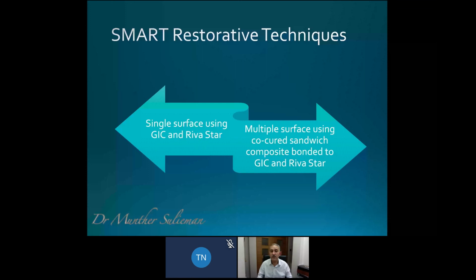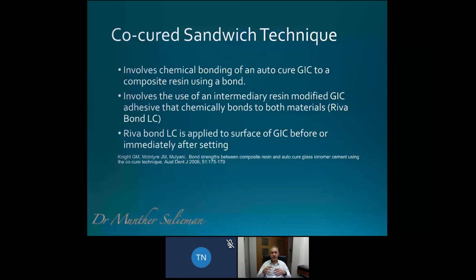The product itself uses glass ionomers just like the original sandwich technique, except in this case, what we're actually doing is we are using a chemical cured glass ionomer, so Riva self-cure or Riva self-cure heavy body. After you've used the Riva Star on a class 2 cavity, you've washed everything out, I then tend to re-etch the enamel of the cavity, and then I've isolated. I then use glass ionomer such as Riva